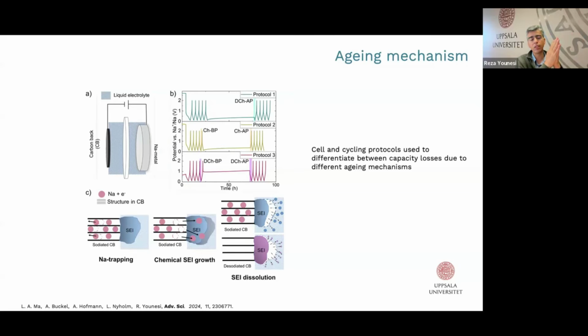This could indicate that some sodium has diffused into the current collector, for example. This is so-called sodium trapping, if sodium is diffused into the current collector and we cannot extract it easily in upcoming cycles.